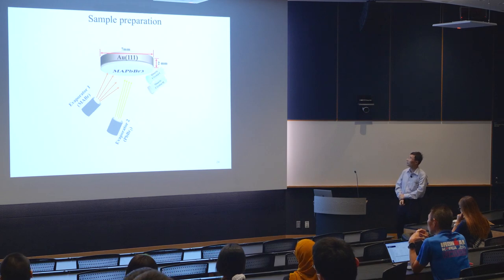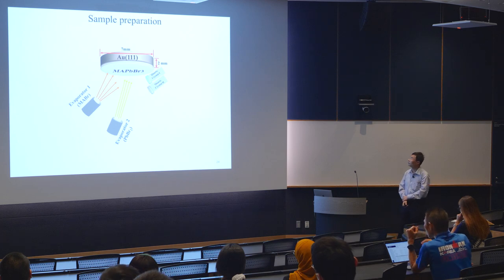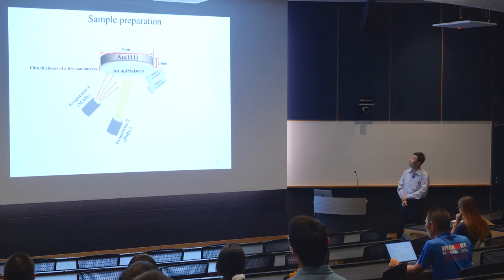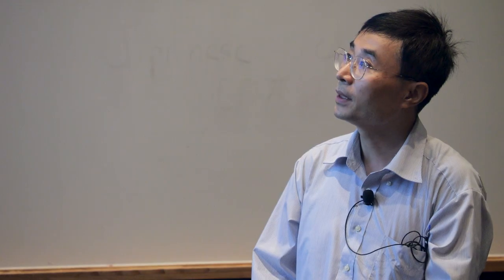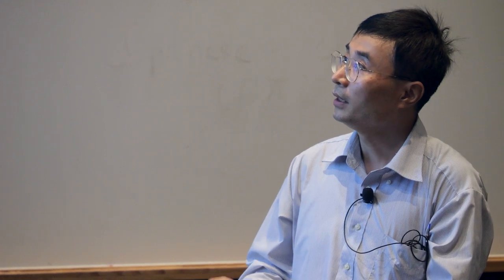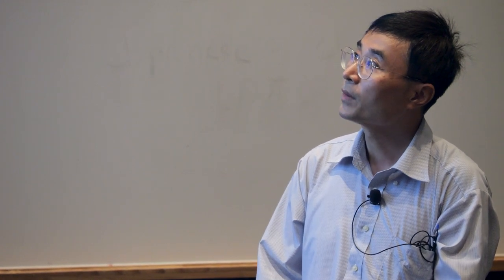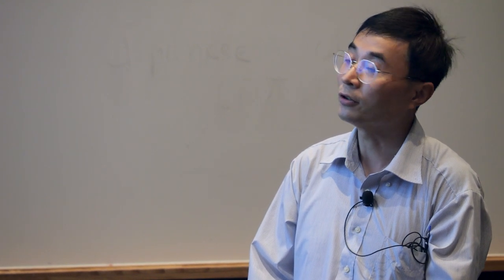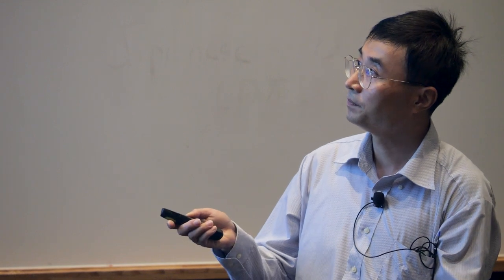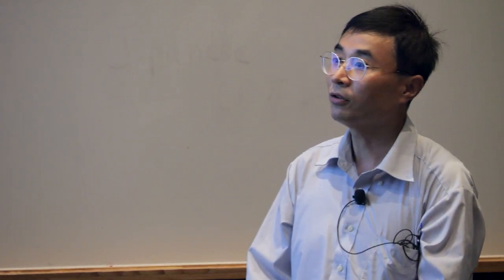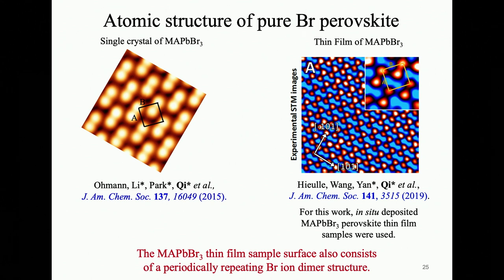The film thickness can be precisely monitored by these microbalance sensors. And we usually grow perovskite thin films with a typical film thickness of a few nanometers. The film thickness here is to ensure we minimize the substrate effect while still ensuring stable STM operation. By comparing very thoroughly the STM imaging results obtained on both types of samples, either vacuum cleaved single crystal sample or in situ grown thin film sample, we found that the results were highly coherent. Therefore, in the following discussion, I will not differentiate between these two types of samples.